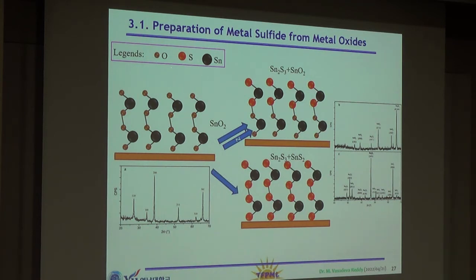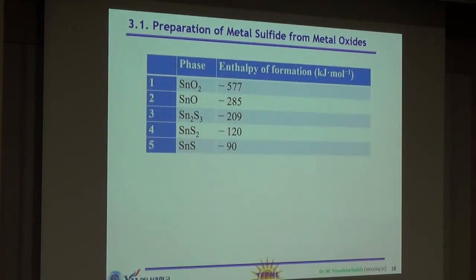Later we realized the formation energies of these compounds. If you see here, the tin oxide forms more easily as compared to the tin sulfide. We need a really high temperature and also special conditions for tin monosulfide. Even when we attempted to prepare the tin sulfide using metal layers, it was so hard to find the suitable area to form the tin monosulfide.